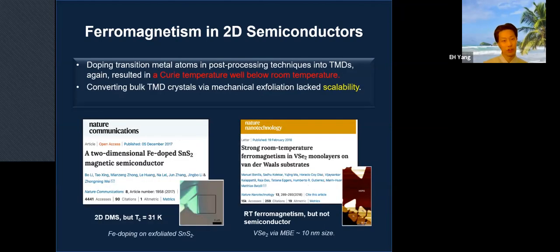Some more approaches include doping transition metal atoms by post-processing techniques into these TMDs. Again, the problem is scalability, because these are dopings of iron onto exfoliated tin disulfide, right? And again, the Curie temperature is only 31 K. Now, there are a couple of papers published in 2017 and 2018 showing room temperature ferromagnetism, but they are not semiconductors. And also, again, still exfoliated. And the example shown in the bottom right is MBE grown. Basically, the flake size is 10 nanometers.